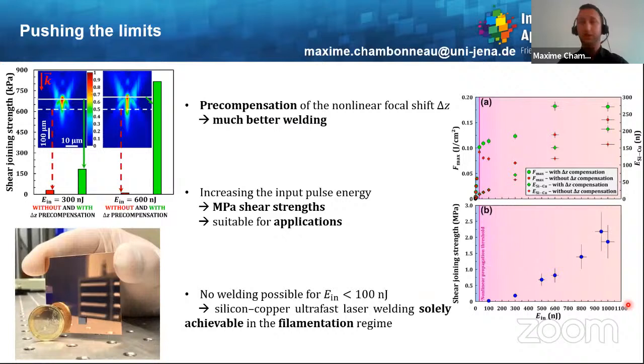Okay, so now that we know the reasons for the nonlinear focal shift and we have characterized the evolution of this nonlinear focal shift as a function of the input pulse energy, let us try to push the limits a little bit. Here on the left, you can see the shear joining strength as a function of the input pulse energy, for two cases actually: without, in red, and with, in green, nonlinear focal shift precompensation. And it is pretty clear from this figure that precompensating the nonlinear focal shift delta Z leads to a much better welding. Okay, so what now if we decide to increase the energy even more, but at the same time precompensate the nonlinear focal shift delta Z?